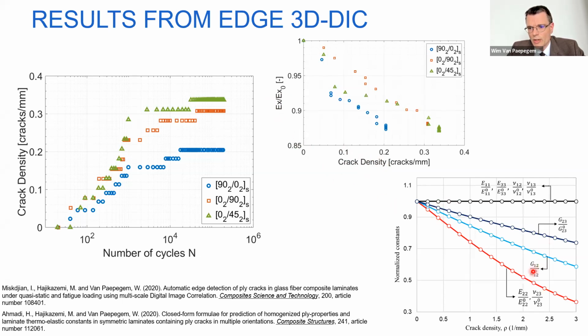Here you see, again, our variational model can say the relation between the crack density and the stiffnesses, all the stiffnesses. So you see if you have some cracks in a 90-degree ply, some stiffnesses just stay the same, but other stiffnesses, especially the transverse stiffness, the shear and transverse shear, they drop a lot. So the nice thing here, and we use that a lot, is that you do not even need to know a damage model in fatigue to have the evolution of damage.